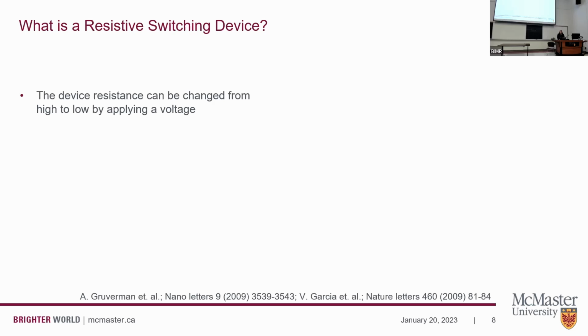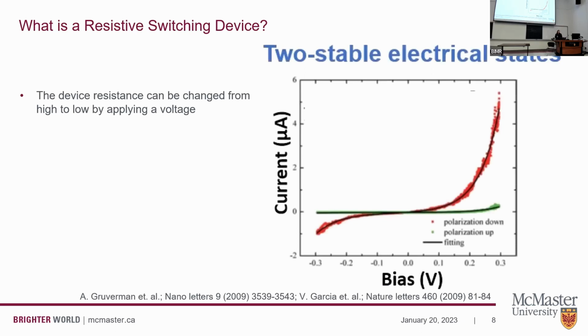In these devices, we can change our resistance by applying a voltage. Here is a typical current-voltage characteristic that we can obtain on a resistive switching device. Here we have an IV curve, and the curves correspond to the results that we obtain on our devices. We can see that we have a hysteresis with two different stable electrical states. In one of the states, the green one, the current is really, really low as we change the voltage. And on the red one, a significant amount of current can flow when we increase our voltage.